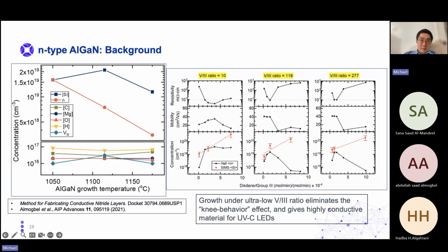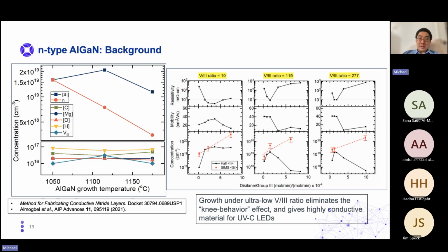So in the diode, the n-type material should be very conductive because, especially for nitrides, the p-type material is extremely non-conductive compared to, for example, p-type silicon, conventional semiconductors, p-type gallium arsenide. So for nitride materials, p-type gallium nitride and p-type aluminum gallium nitride are extremely non-conductive. The n-type needs to be extremely conductive to spread the current well throughout the entire device.